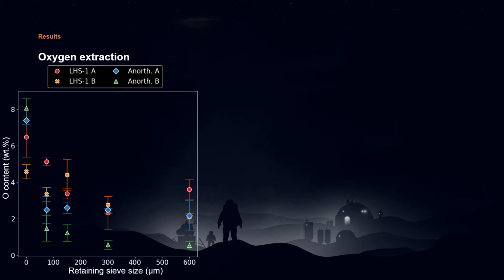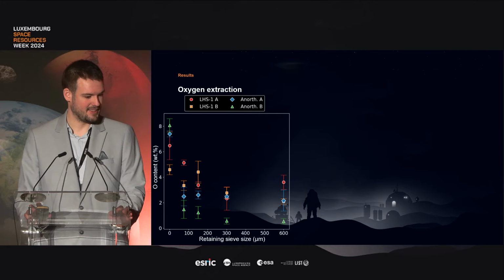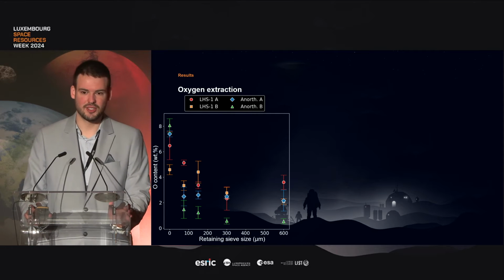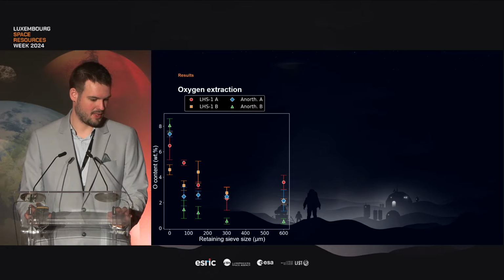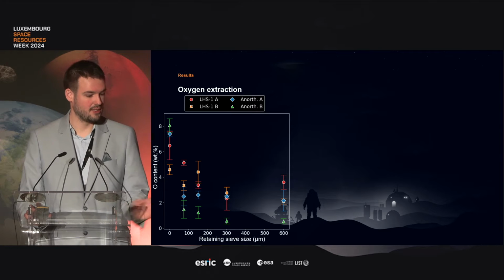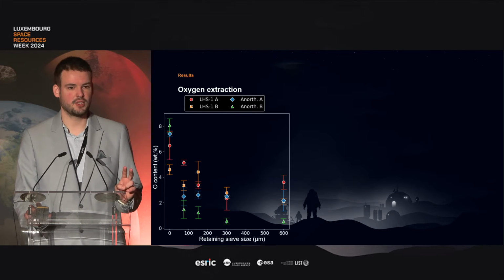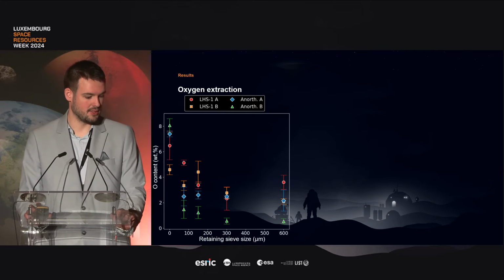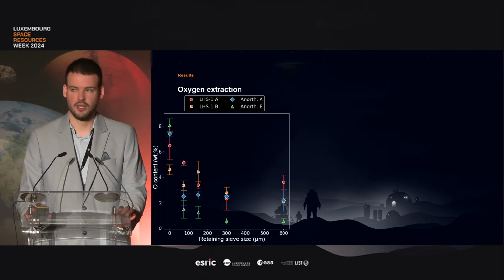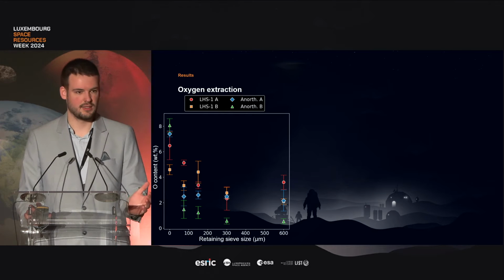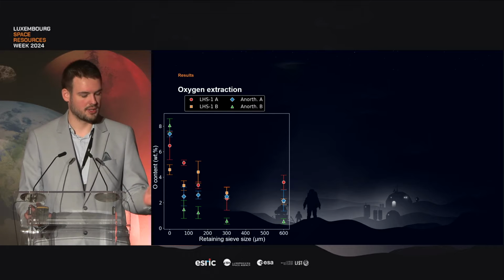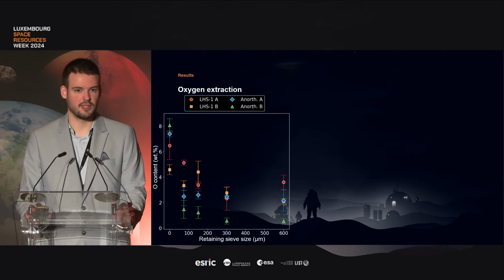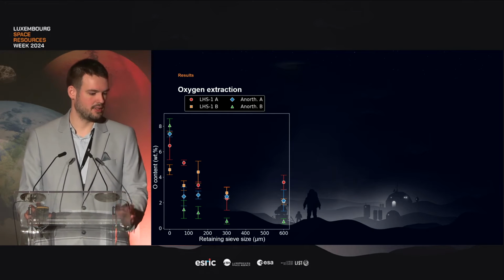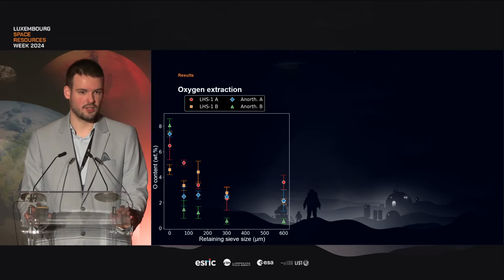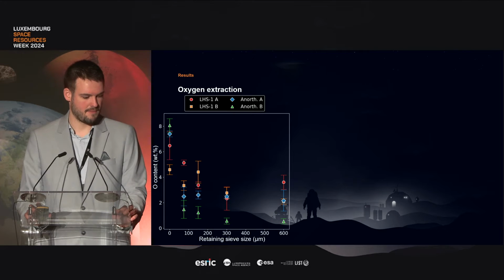Going from here, I'm going to go into the results. Being a PhD student, obviously I have a lot of graphs to go through. The first of all being this one: oxygen content of the products obtained for 4 experiments, 2 with LHS1 and 2 with anorthosite, depicted here across the different size fractions. What we can see from that mostly is that most of the product is below, let's say, 4 weight % oxygen, with a slight increase on the smallest size fractions, so on the very fines.